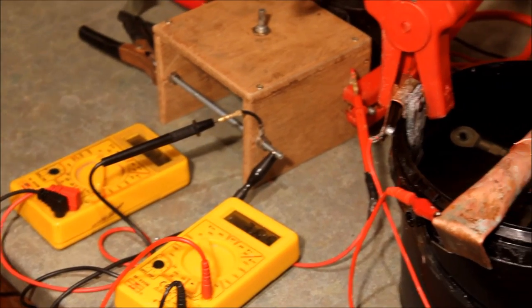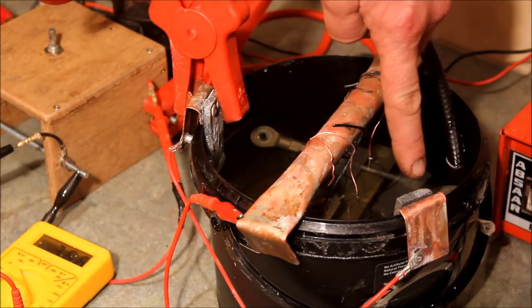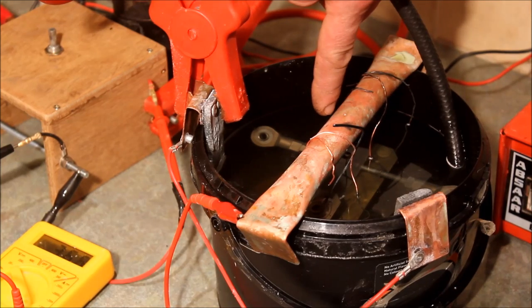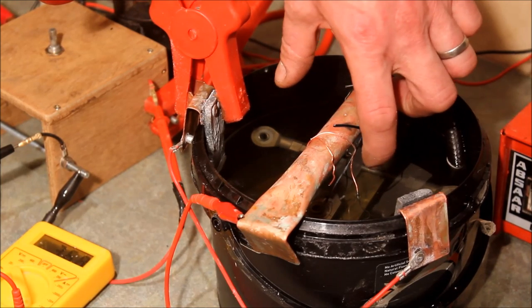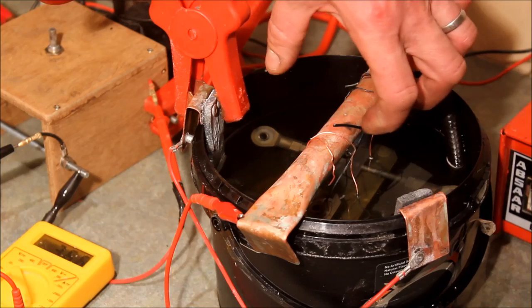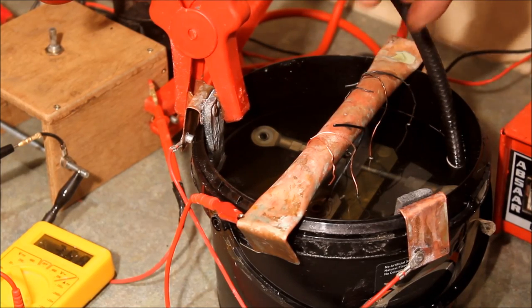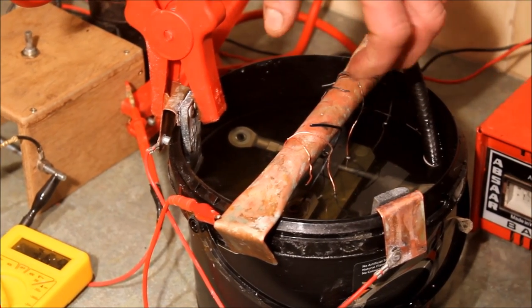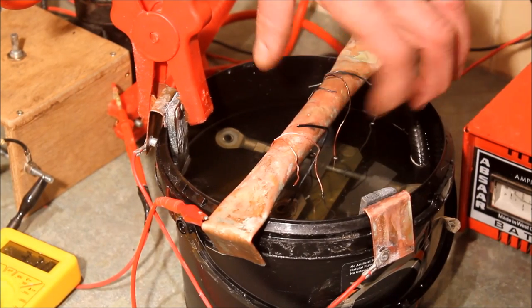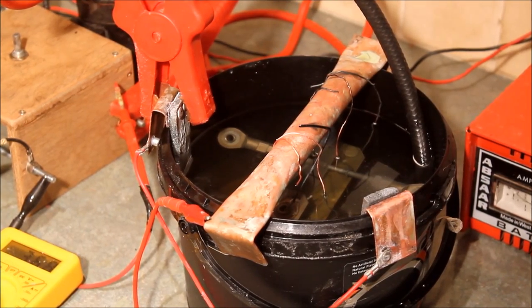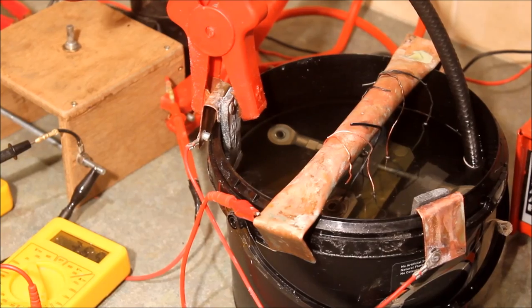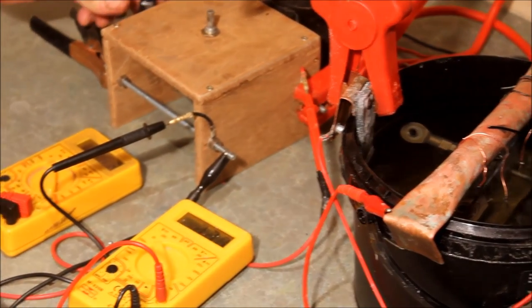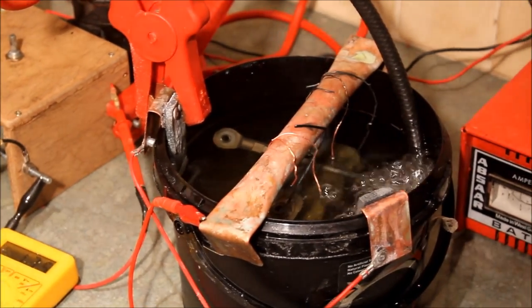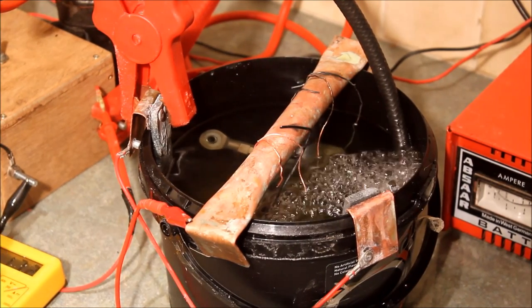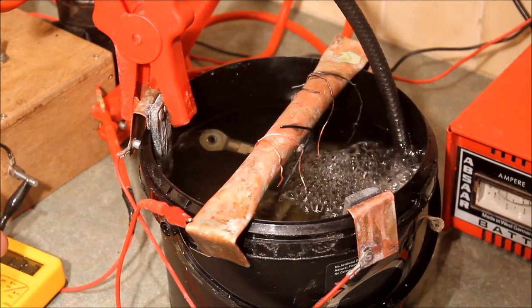The other thing to bear in mind is that things that are closer to the anodes are going to plate more than things that are further away from the anodes. Things that are facing the anodes are going to plate more than things that are hidden from the anodes. So try to move the pieces around periodically if you can, and that will give you a more even plating all over. The only other thing though is to connect our agitator, our aerator, and leave it there for, well, we'll knock the time down now to about just under an hour.